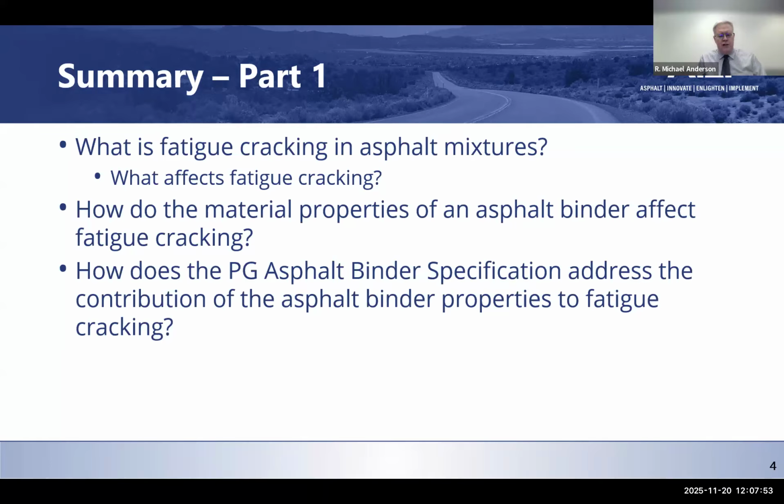As far as what affects it, asphalt mixture stiffness is a big contributor to that, which is a function of really a lot of different things, but the in-place air voids, the volume of the asphalt binder that's in the mix, the asphalt binder stiffness itself, and how that age hardens.